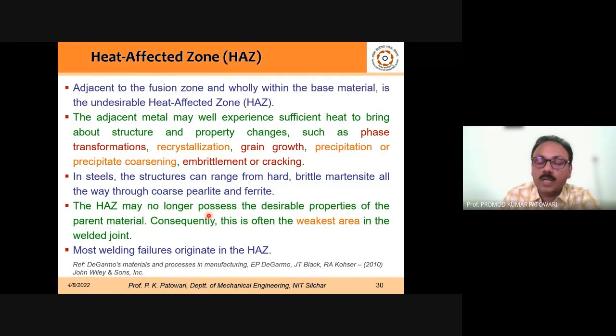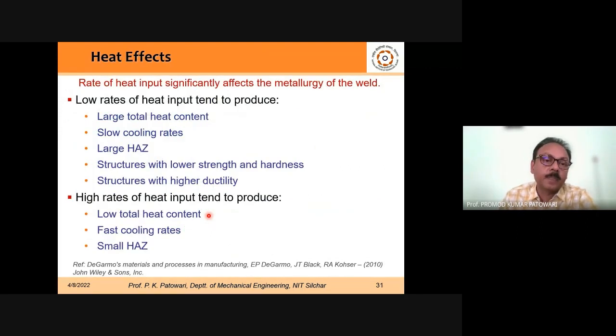Now, we are going to look at how this can be minimized. If you look at the delivery of heat energy to the workpiece material, it can be in two different ways. One can be a low rate of heat, meaning you are giving a smaller amount or lesser intensity of heat, and very slowly you are applying the heat to the product. Before making any changes in the material, that heat may get dissipated inside the material in a very unwanted way. So ultimately, we are getting a large total heat content because the heat is getting dissipated. And to melt that material, we need to reach that temperature so that the material may get fused together. So we need to raise the temperature.